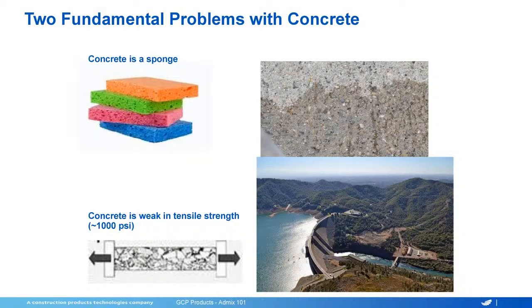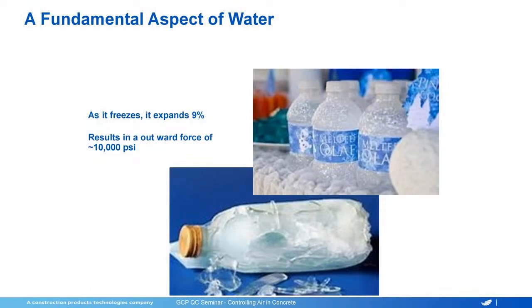Okay, so concrete is a great product, as we mentioned. However, it is a sponge. It is not waterproof unless you do something to make it so. And it's also weak in tensile strength. So we have a material that will absorb water, allow water in, and it's weak in tensile strength. And then, as we all know, water expands when it freezes, and it expands about 9%. So it's going to grow, and the outward force is at about 10,000 PSI. So it's a lot of force. And again, that's internal, so it's tensile. So our concrete is not able to withstand that. So the concrete gets wet. It can take it for a little while, but after repeated cycles of freezing and thawing, it will fail if it's not properly air entrained. And there's some other things that go into freeze-thaw durability that we're not going to spend a lot of time on here today.